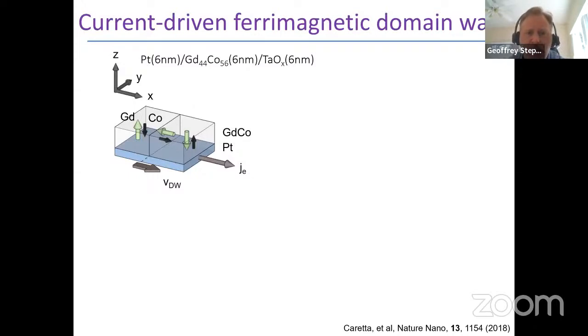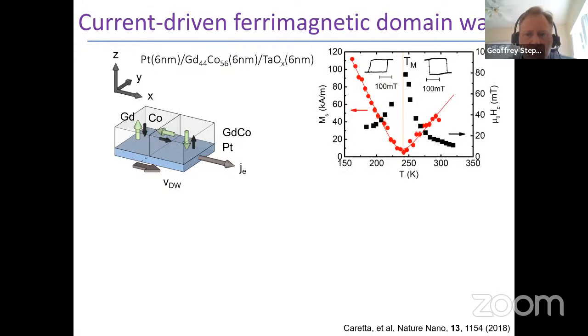We've looked at the same phenomena in the same material class that I showed you, in which we can achieve very small skyrmions. So a cobalt gadolinium alloy, in this case driven not by magnetic fields, but by spin orbit torques, using a platinum layer adjacent to the cobalt gadolinium as a spin current source. And in these materials, we have a compensation temperature that's a bit below room temperature. And so by using a controlled cryostat, we can tune through compensation and explore the current-driven dynamics.